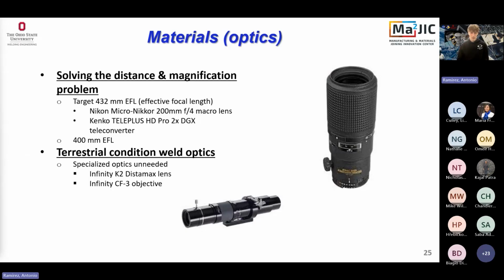So to solve the magnification and distance issue, we use some special optics here. Running the calculations for focal length, we wanted to target a 432 millimeter effective focal length. As it turns out, this is quite hard to do with our minimum distance of 20 inches. You can get a higher focal length if your minimum distance away from the thing you want to view is farther.